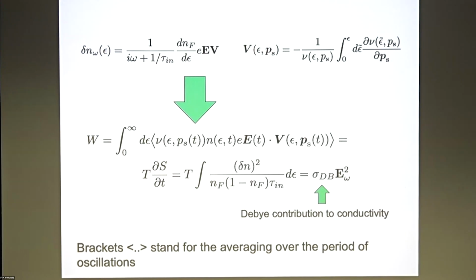Something to retain. So you're talking about thermally excited quasi-particles? No, they're not thermally excited. They already exist. They just move. So there is a thermal distribution. But you need a thermal distribution. Can I put the temperature to be 0? No quasi-particles, nothing. Can you wait? No, I mean, okay. Let me. Yes, you can. The amplitude of the effect will be the same, but the frequency interval where this effect will be not 0 will shrink to 0 as your temperature goes to 0. That's my answer.